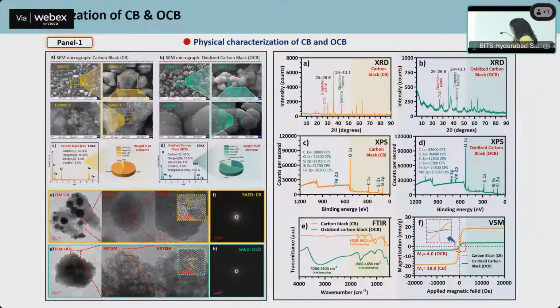With this, he characterized the material to understand its morphology and elemental composition. You can see that CB looks like a granular morphology. These are magnified images of the same. However, OCB looks like a particulate morphology after oxidation. The EDAX elemental composition of CB and OCB shows the presence of iron, and there is an increase in the oxygen content in the case of OCB.